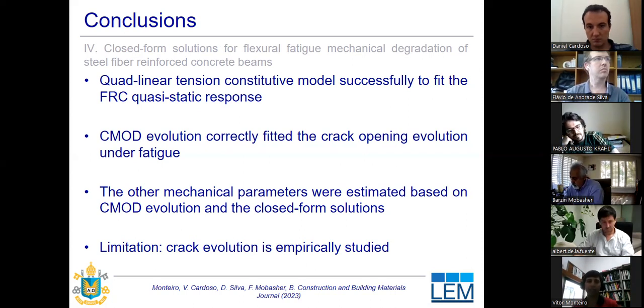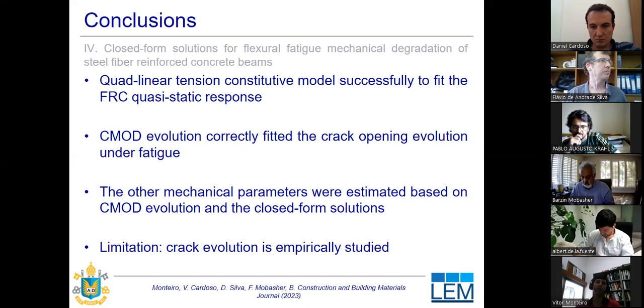The major limitation of the model is still the crack evolution, since we used an empirical equation, it needs to be calibrated for any kind of material that we are studying, since it is empirically based on past results. Therefore, one major limitation is this degradation of the CMOD, and probably the major step that could be done after this research is developing a more adequate and more robust model based on fracture mechanics to evaluate how the crack and the CMOD evolve with the fatigue loading.